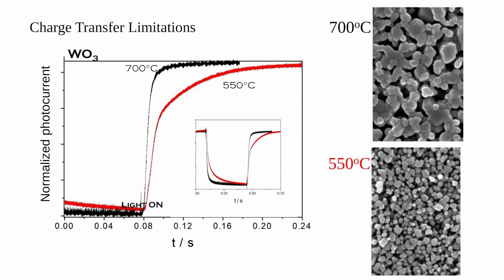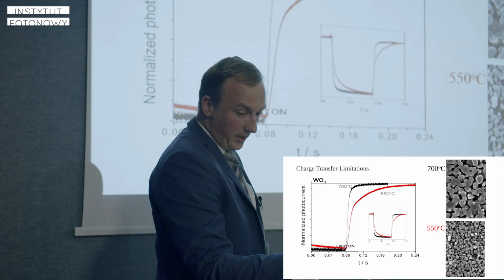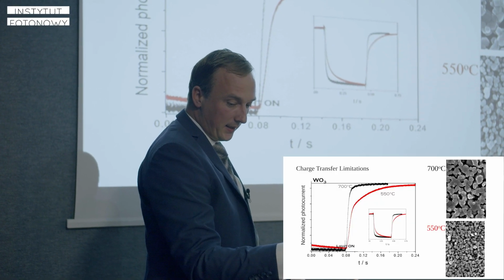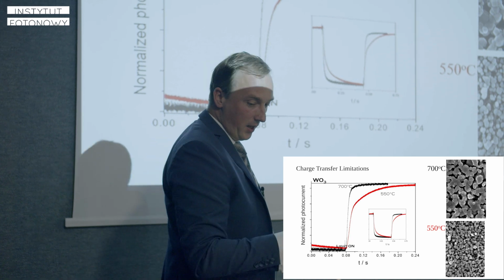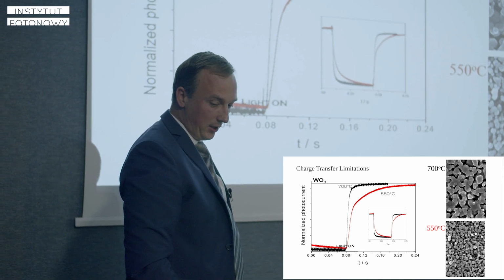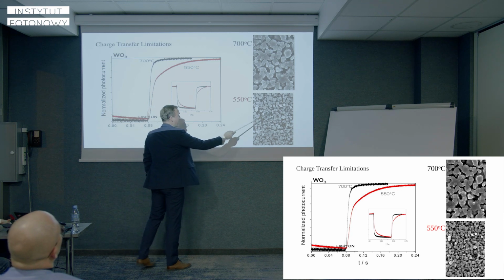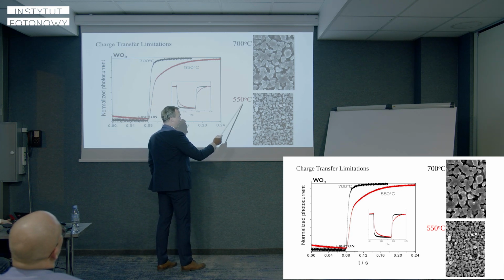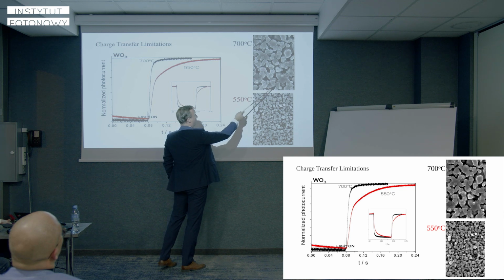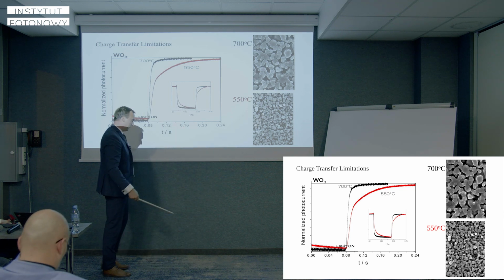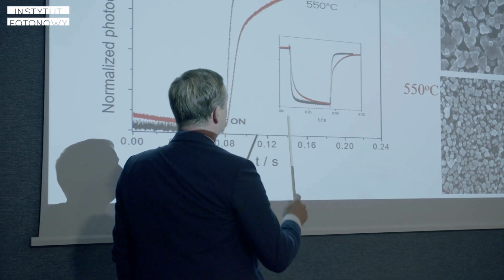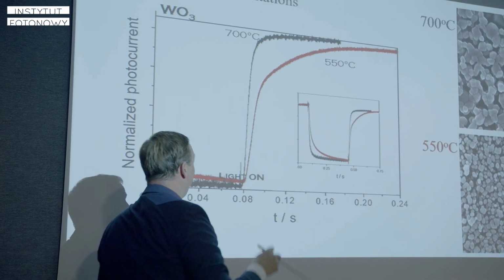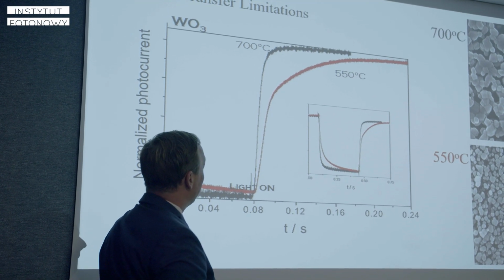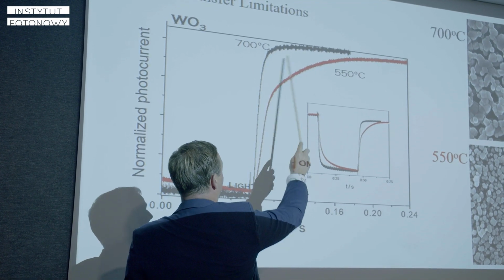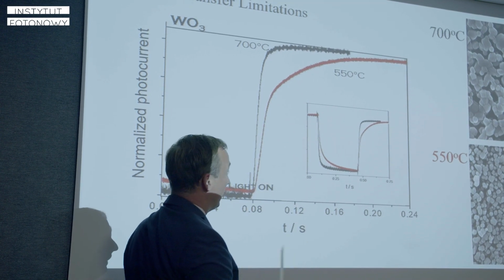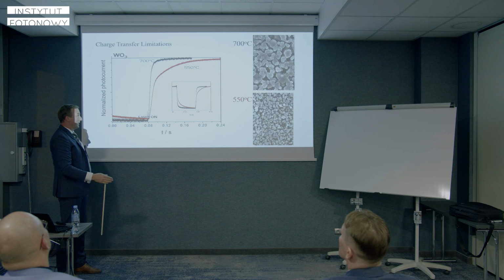So the surface structure of the semiconductor is very important. When we increase its crystallinity as well as the pore size, we influence the kinetics of the photooxidation reaction. So this is tungsten trioxide heated at 550 degrees Celsius, and we heat it more to 700 degrees Celsius. When we look at the photocurrent response, we can see that the kinetics of the creation of the photocurrent is much faster when we have more crystalline structures.